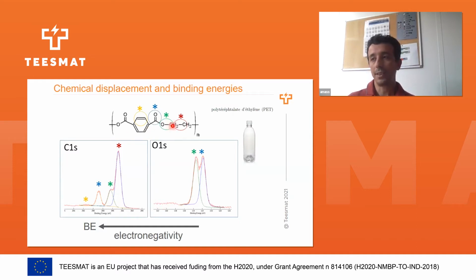We can see that the first carbon is bonded to carbon. Since carbon is less electronegative than oxygen, its binding energy will be at a lower position. The more electronegative the neighbor, the more the shift goes to higher binding energy. So that is how we may link our spectrum to the chemical structure of our materials. There is a strong correlation between the electronegativity of the surrounding atoms, the chemical structure, and the binding energy that we observe in the spectrum.